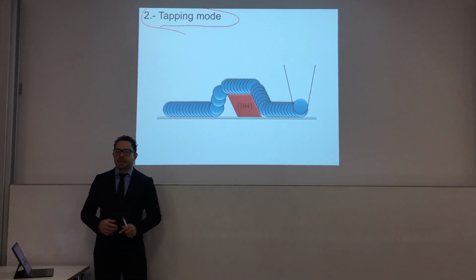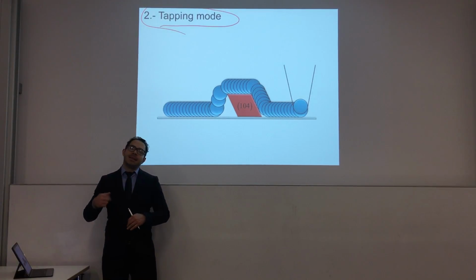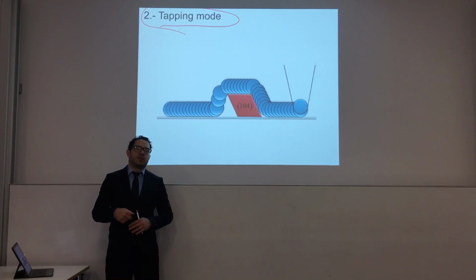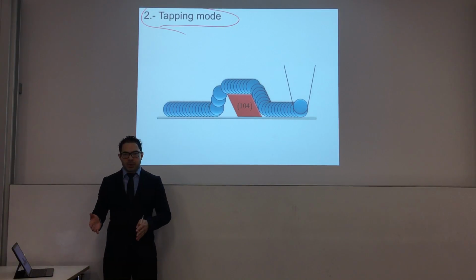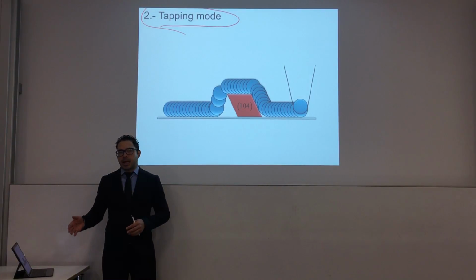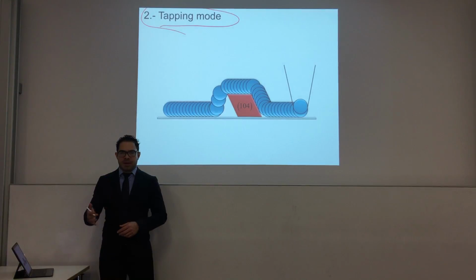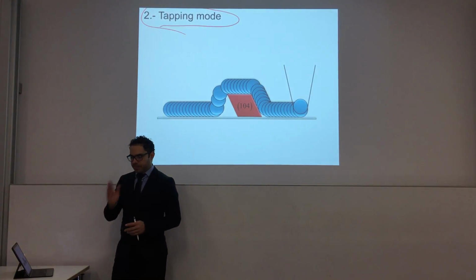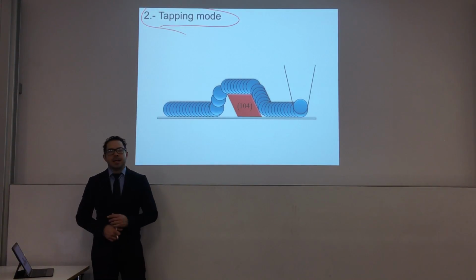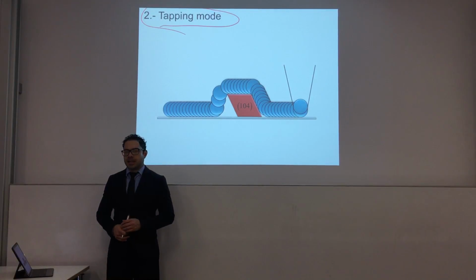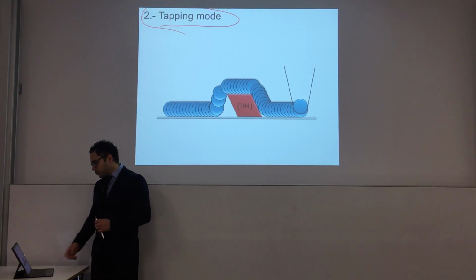What tapping mode does is that you have the tip, and the cantilever makes the oscillation of the tip at a given frequency. This frequency is set externally by a piezoelectric, and usually we choose a resonance frequency of the mechanical system of the cantilever. So we excite it in such a way that it will be very sensitive to changes in the amplitude also.